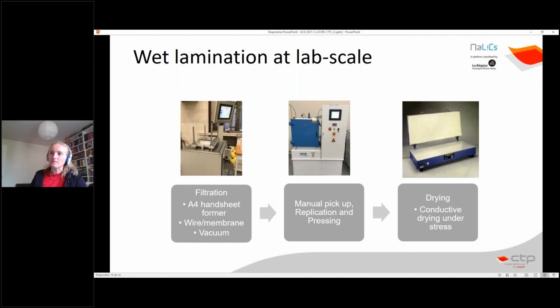that is used, and the idea is simply to filter an MFC suspension on a wire using some vacuum. Then to replicate this MFC film on a paper substrate. And then using a plating press that you see here in the middle to press the MFC film and paper together between blotting papers in order to join the two layers, and then to finish drying the material using conductive drying under stress, for example, in a flat dryer or in a half moon dryer. And then when you peel the blotting paper, you have the remaining MFC wet laminated paper.